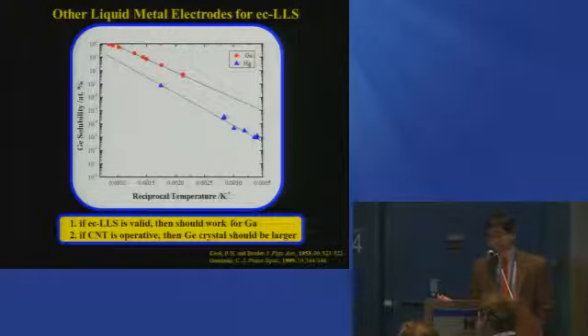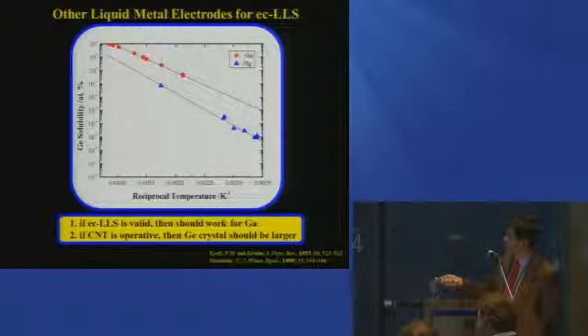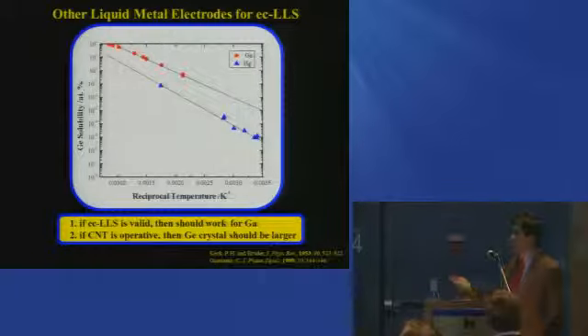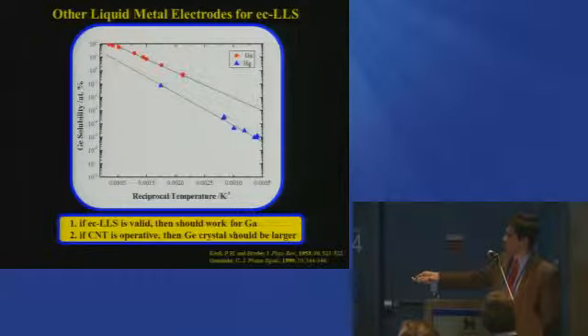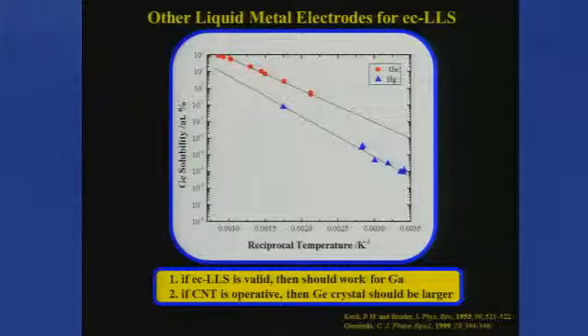To grow better crystals, we have invoked the same ideas that you would to grow better organic crystals if you're a synthetic chemist, and that is to change the solvent. Mercury was the easiest solvent to think of as a liquid metal electrode. The next easiest thing to think about is gallium. Gallium is also a liquid at room temperature. It happens to have the property that at room temperature, which is right here on this reciprocal axis, it's about 100 times better at dissolving germanium than mercury. And so if our whole idea of ECLS is right, this process should work for gallium, and it should produce higher crystalline quality materials.